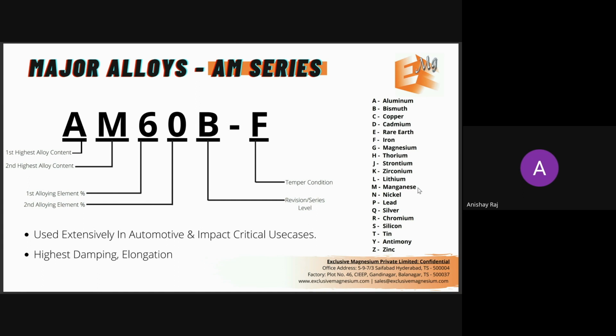M is for manganese. So aluminium is 6% or 5%, then manganese is less than 1%. This is the second alloy series, which is the AM series. Now this has very high elongation and damping coefficient. So it is usually used in impact critical components. For example, all steering wheels in India are made out of this alloy, because it's a safety feature.